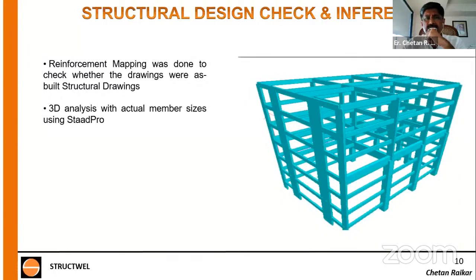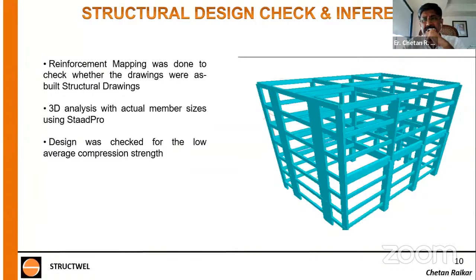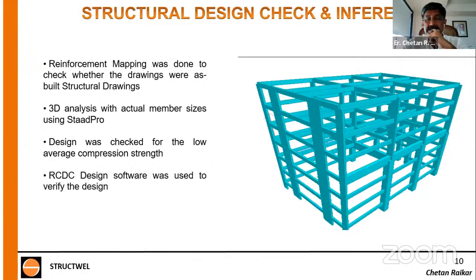3D analysis with actual member sizes using StaadPro. Design was checked for the low average compressive strength. I just showed you in the previous slide that though the design compressive strength of concrete was expected to be 30, on site actually it was about 21. So we used 21 as the compressive strength of concrete and did the 3D analysis. RCDC design software was used to verify the design.